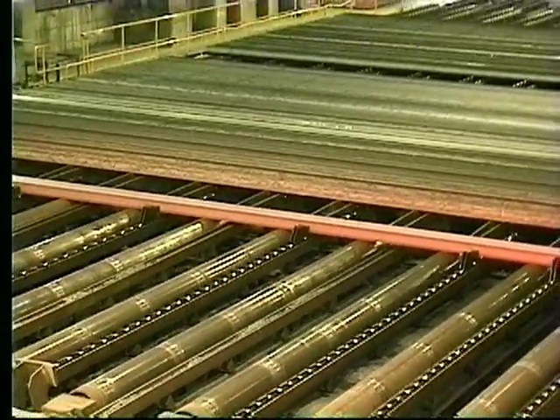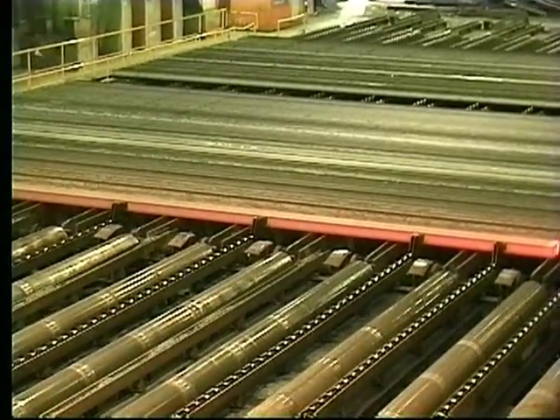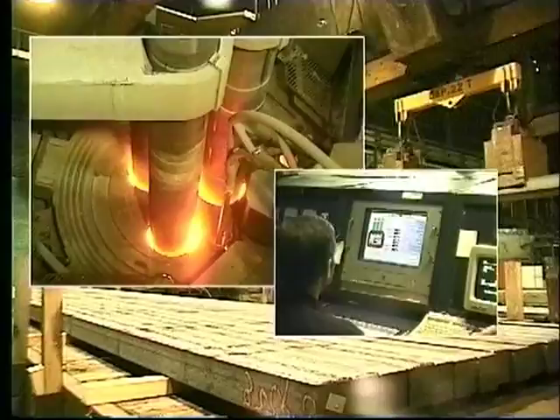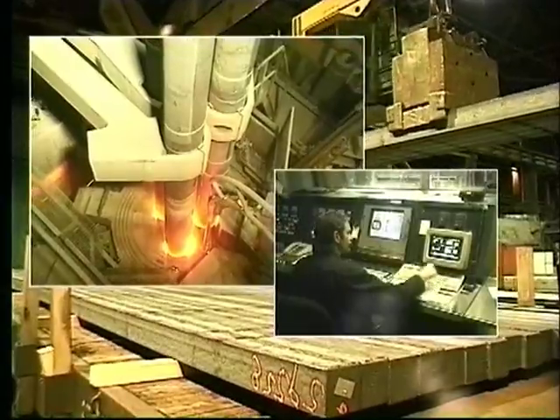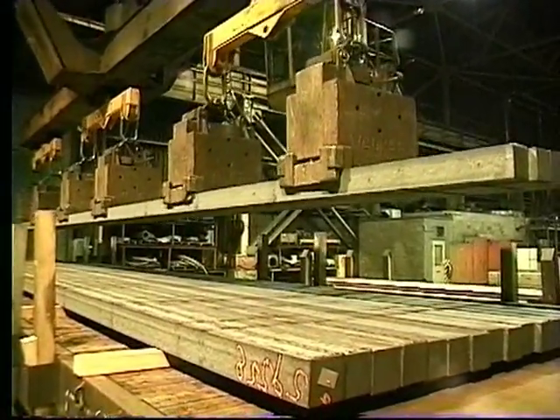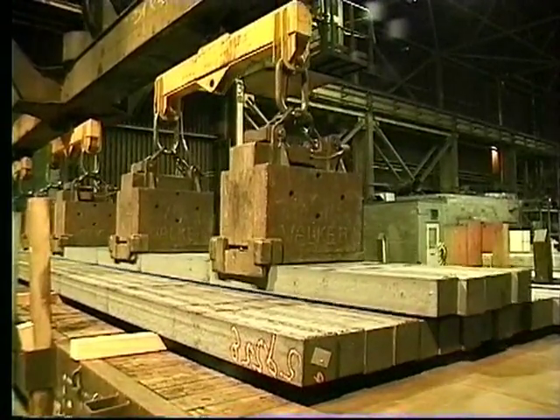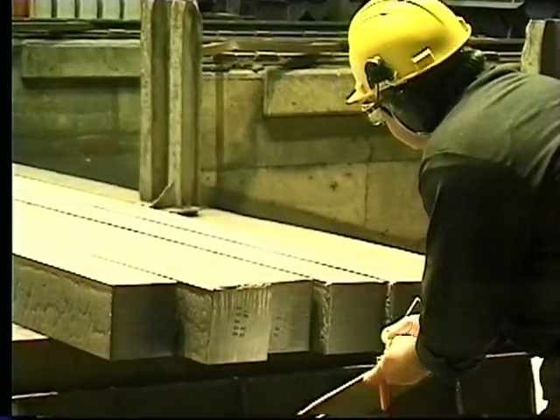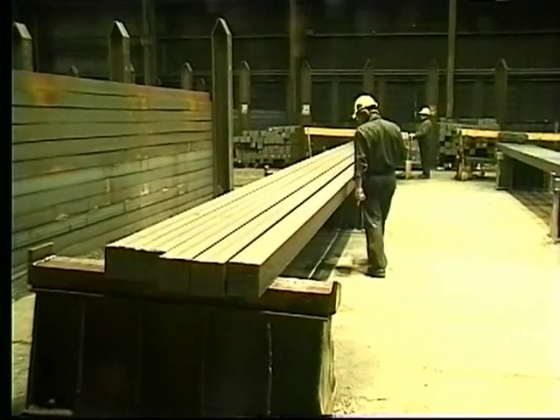QIT's steelmaking and casting operations employ the latest computerized equipment and procedures, including automated alloy trimming, argon stirring, wire feeding of aluminum, carbon, and calcium silicon at the ladle treatment station, automatic tundish and mold level controls, and 3-zone fully instrumented secondary cooling. Computers monitor any deviation from standard operating practice and promote quality through individual billet tracking and selective inspection. QIT supports this approach to quality by a final inspection of shot blast billets according to a predetermined sampling pattern.